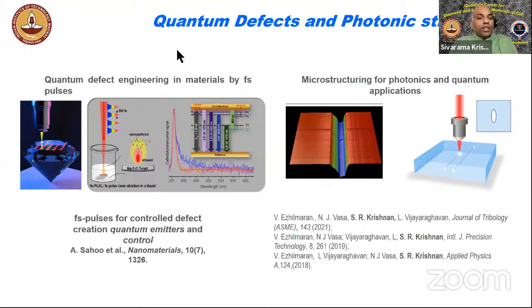So one way is to use very short pulses and in a very minimally thermal way create defects, which essentially you can think of as origins of color in materials, very prominently our favorite diamond, but also another very prominent material which this group has a lot of research invested into, which is zinc oxide, where, for example, we demonstrated in the left part of this figure that we can indeed control the emission by synthesizing these nanoparticles and ablating them with very short laser pulses.